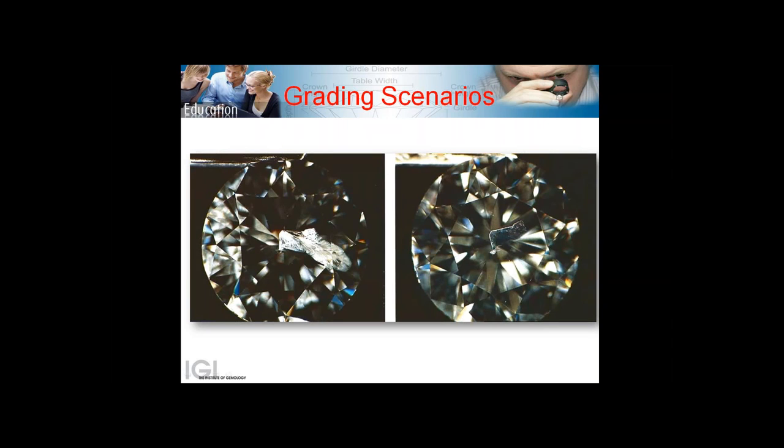When they're using glass, the refractive index of glass and diamond are very similar, so you cannot now see the feather, you see through the feather. But from the pavilion, if you see a single color flash coming from a crack or a feather, this stone could be enhanced. All right. So this is a particular stone which is enhanced.